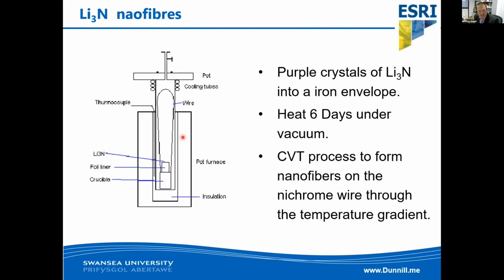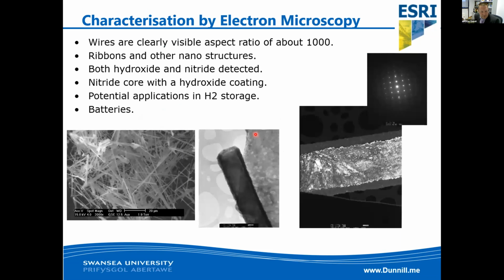Under massive vacuum, you can heat them up with a temperature gradient, and you can do a chemical vapor transport reaction to actually move the lithium nitride and form nanofibers on the nichrome wire throughout the temperature gradient. Really interesting synthesis to get some nanofibers. We can see we get fibers and wires with quite a high aspect ratio. We get ribbons and other nanostructures as well.